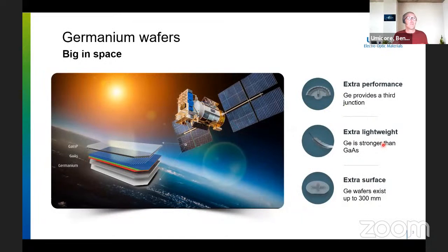Why is that? Because germanium has been used for the last 20 years as a substrate material for solar cells used in satellites. And it's a triple junction solar cell, so very efficient solar cells. Actually, the satellite business is the most important one and interested in this technology because it's rather expensive. It's using epitaxial growth of gallium arsenide layers onto germanium, so it's much more expensive than silicon. And in space, lightweight, very efficient cells is still very important.